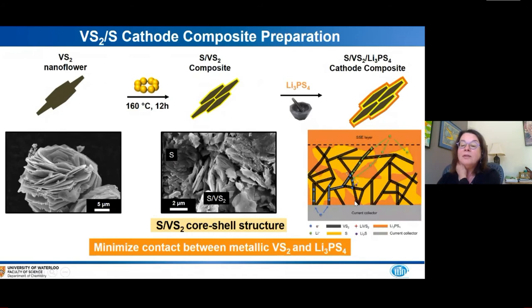This is the concept here, where we have these highways of VS2 providing electrons to the system, but also providing lithium ions to the matrix of the sulfur, shown here in yellow. The matrix of the solid state electrolyte then serves as a conduit for the lithium ions in this complex structure, and we use lithium thiophosphate as our solid electrolyte, at least in these initial studies.